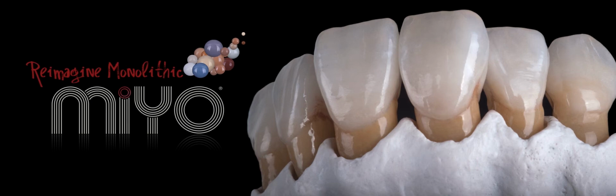Most of your zirconias are somewhere in the 10.0 to 10.3 range. Lithium disilicate, very, very similar. So the CTE of the MiYO material is perfectly matched to this range of materials. So yeah, you can use it with any zirconia.